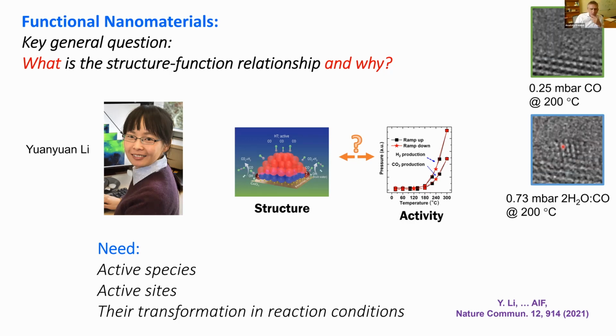And so in this case, after solving this structure-mechanism relationship problem, we understand that there are some sites on the particle that are active for forming hydrogen and carbon dioxide. And those sites are on the perimeter. You don't see them because they're really dynamic. You see that there are other sites, but those on the perimeter where my cursor is, those are really going in and out of focus. And so this was pointed out to be the active sites. And there is an interesting mechanism there, and it was just published a few months ago, and my group member Yuanyuan Li was the lead author on that.